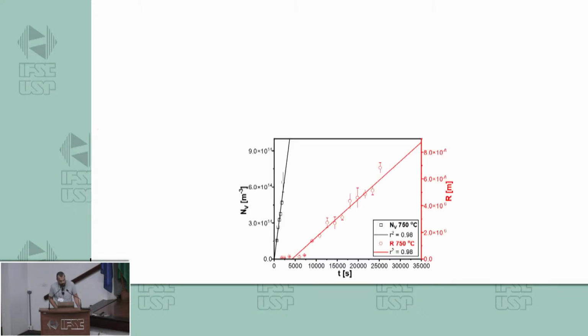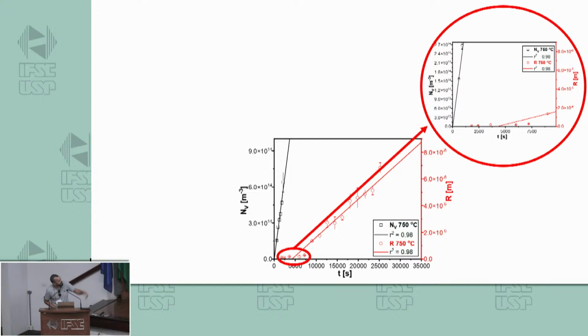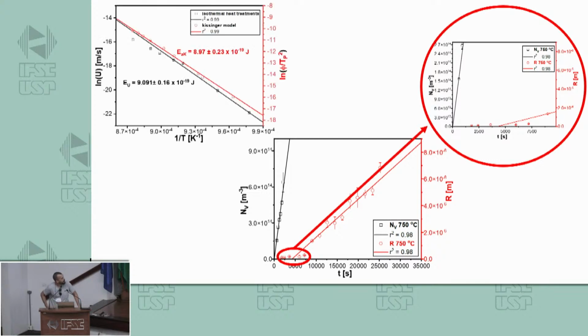The next result, about the crystal growth, showed that below the induction time for crystal growth, another slope is verified, as we can see here in this graph, the red points. Probably another diffusion mechanism occurs in this region. Finally, the final result showed that